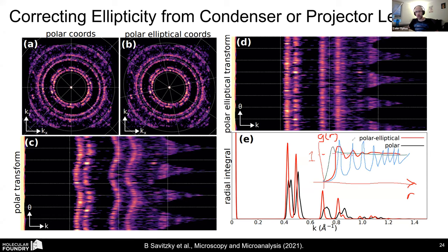So all of these tools are built into py4DSTEM right out of the gate. All you have to do is find the center of your diffraction patterns, do the elliptic correction, radially integrate it, and then just do the RDF analysis here. And that can be done probe position by probe position. The complication is RDF mapping works reasonably well if the sample is below, say, 10 nanometers, 20 nanometers, but most materials that we look at are thicker than that. And so we're investigating using machine learning to remove the multiple scattering from these patterns right now. So I actually think it's going to be a huge growth area of using the electron beam to study disordered materials.